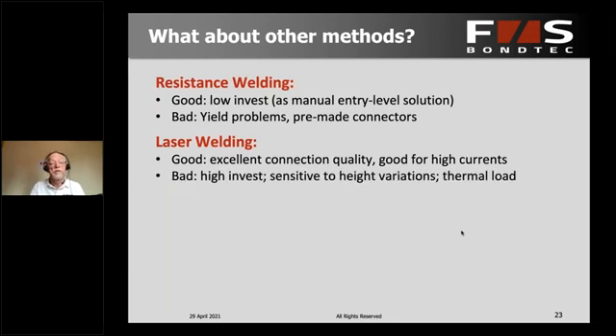But the drawback is, again, it's quite an involved technology. The initial invest is rather high. So if you start out in this business, it can be daunting to have such a high investment. And you are much more sensitive to height variations between the connectors and the cells because you're really dependent on the welding gap. You also have a thermal load because this is a real welding process with a molten phase, so you have to worry about that.